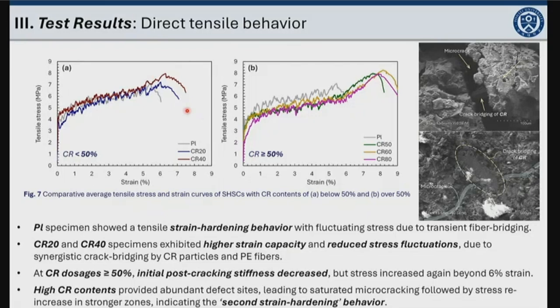However, when the replacing ratio was 50% or higher, the initial post-cracking stiffness was obviously reduced, and there was a re-increase of the tensile stress, indicating the second strain hardening behavior.